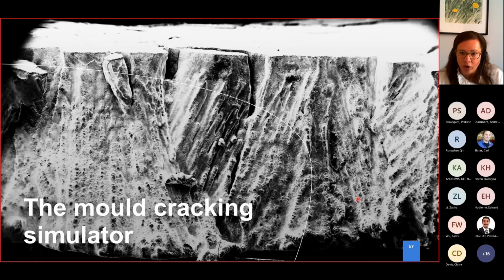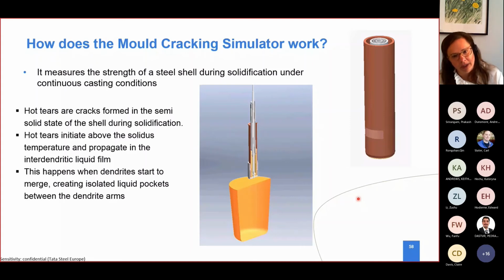The mold cracking simulator. So, going to the dynamic part of it. This is something we have in-house. What it does, it creates, oh, I think the videos are not working. So what it does, it creates a steel shell around a water-cooled copper tube. So it has exactly the same heat extraction conditions as a continuous caster mold. Once it has been submerged in liquid steel, it creates a shell, and this half ring wedge is pulled outwards, pulling that just-created steel shell.